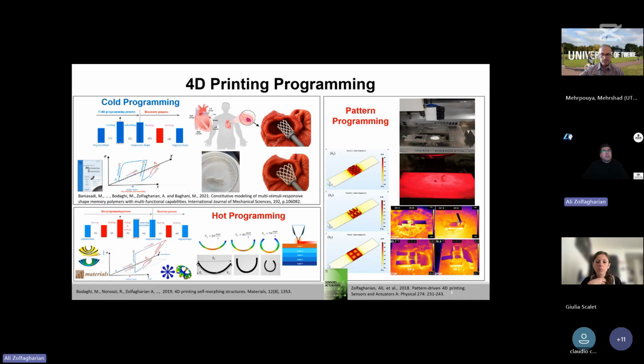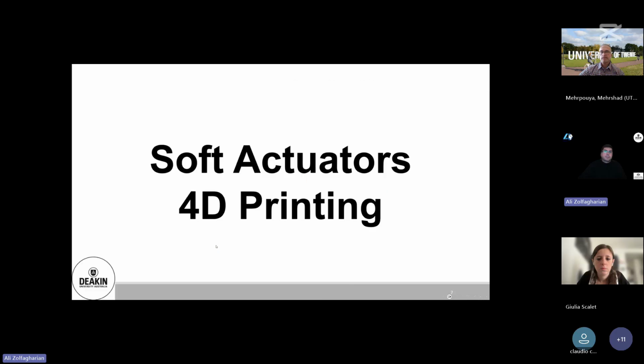And the most genuine approach that we came up with for 4D printing programming is hot programming, where during the manufacturing, using the printing process parameters, we could embed the amount of bending or morphing that we could harness after printing by applying stimuli such as magnetic field, heat, electricity, or so on. For example, in the bottom image, using different velocities of the nozzle, we could come up with functionally graded materials, harnessing different amounts of bending after applying the heat.